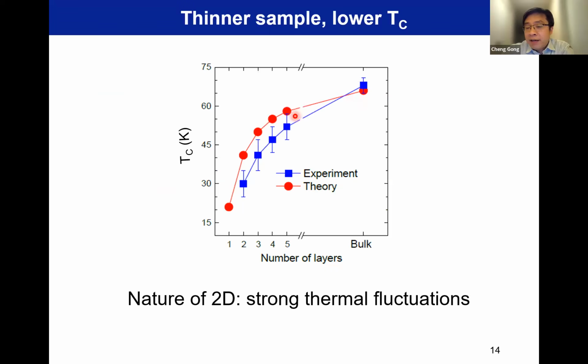So you indeed have such a dimensionality effect that has been observed many times in the traditional magnetic thin film. That indicates in this 2D system, there is indeed a very strong thermal fluctuation that causes the reduced TC. This is also one fundamental reason why it's so hard in early days to observe 2D magnet. Samples sometimes are not so air stable, and signal from the atomic thin micrometer size sample is also not as strong as a bulk crystal. So there are many challenges associated with the observation of magnetic signal from that small flake.